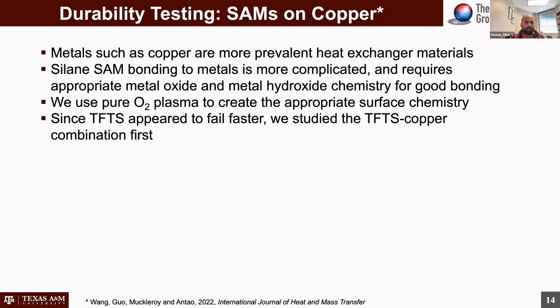for the plasma treatment. The one aspect that we've not yet tried, but I do want to try, is using an oxygen and water vapor plasma, in order to create the right chemistry to get the best surface bonding on the surface. And that's something that is going to happen in the next 6 months or so.